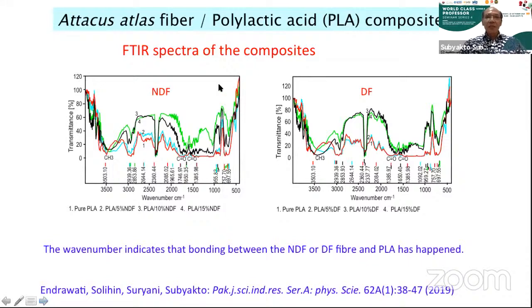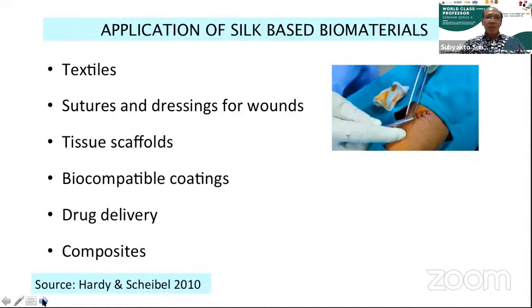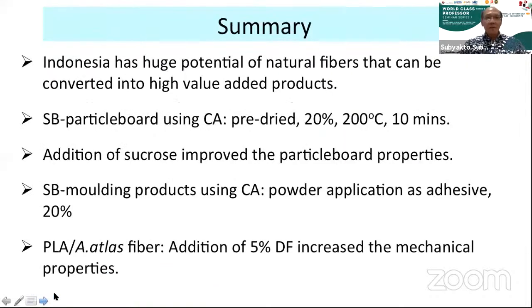And this is the FTIR spectra of the composite. This is just to prove that using the fibers and PLA, this bonding already happened. This is the application of the silk waste biomaterials, especially for textile and medical appliance, and also the composite.